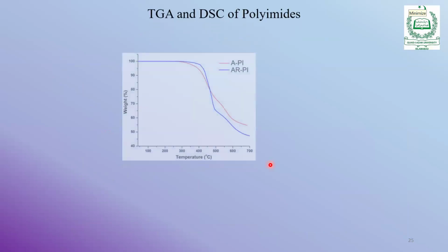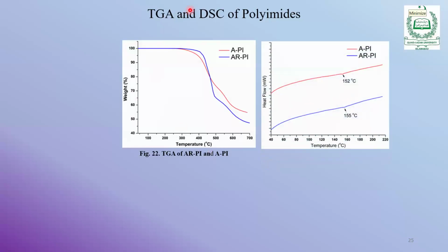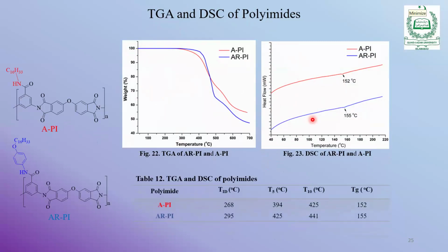Now, for a robust polyimide, we know that thermal analysis is used. This is the thermogravimetric analysis of the two polymers, and this is the DSC, or differential scanning calorimetry, of the two polymers. So you see that these are quite stable. After 250 they decompose. So the initial decomposition temperature for one is 268, and for the second one is 295. And these are the 5% weight loss temperature and 10% weight loss temperature.